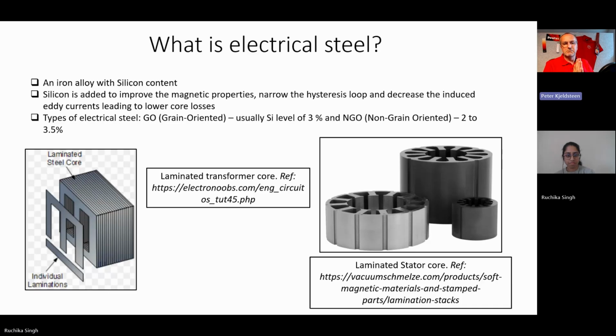Typically, this is made in very fine iron with a little of silicon, so the saturation level is theoretically around 2. But then you add this isolation film on each layer. Does that take up any space? Does it reduce the saturation level? And then the more layers you have, the thinner you go, the more intermediate layers you must have, meaning that the saturation level of a 0.1 must be smaller than 0.35, or how is it?